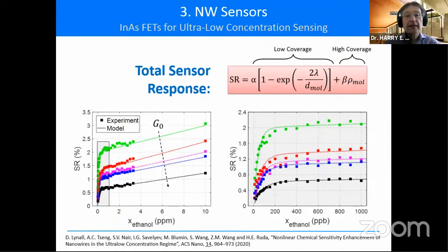So in that case, now we're looking not at the left-hand figure, which was the high exposure figure, but we're blowing up the little square box in the left-hand figure insert in the ppb, not ppm range, which is what you're looking at on the right of this figure. And the total sensor response, of course, is the sensor response due to both of those effects, and you can see that we can completely fit the response. So we can completely explain how these sensors are responding now, right down into the few molecule regime.